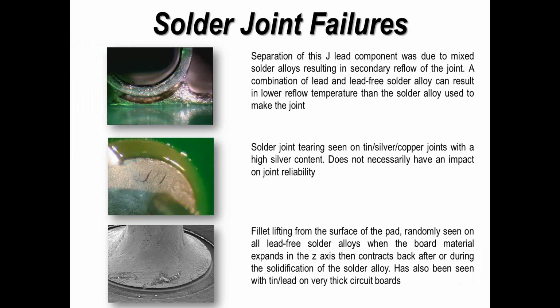And this happens more commonly than you might think, but because nobody normally inspects at this high magnification, you don't see it. I have had this on quite a few processes that I've examined for companies, and in all honesty, there's two ways around it. Change the alloy. So if you're using tin copper or much less silver, you won't have the issue. But in all honesty, I've never ever seen one fail.